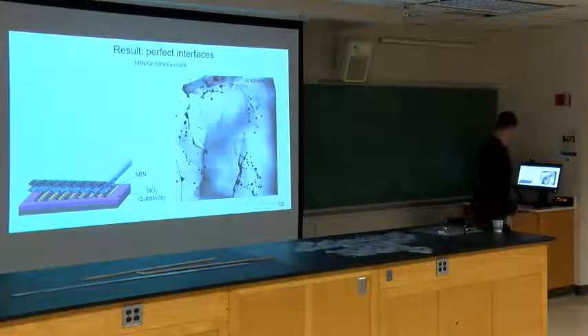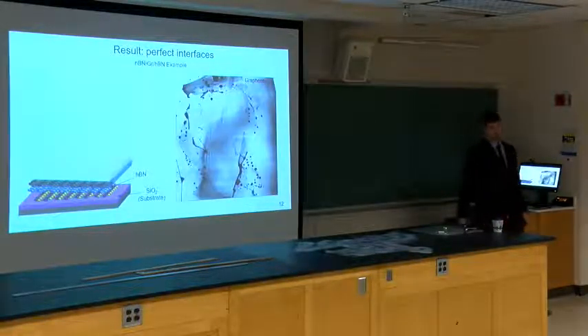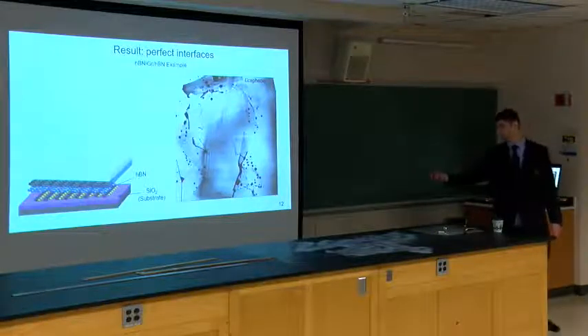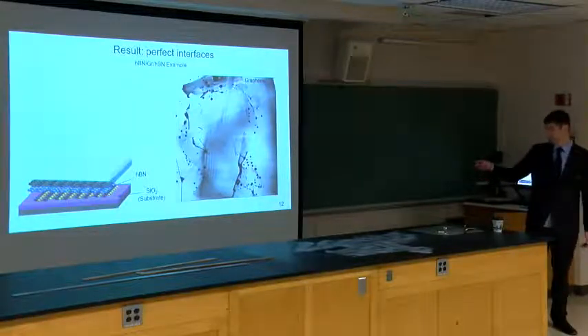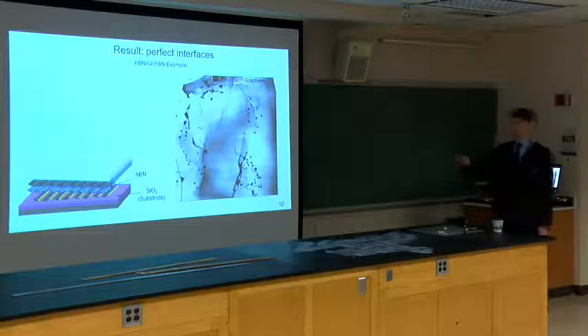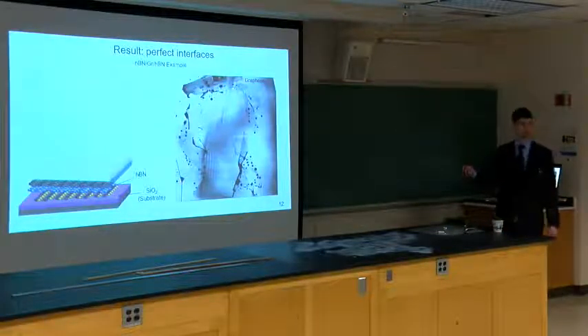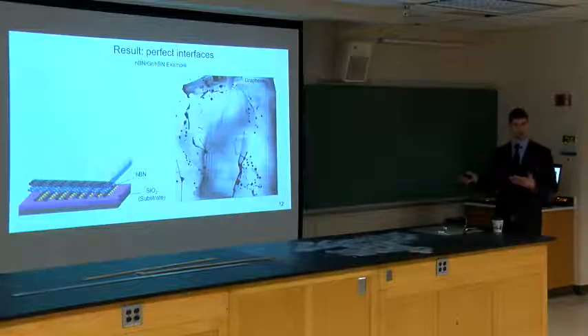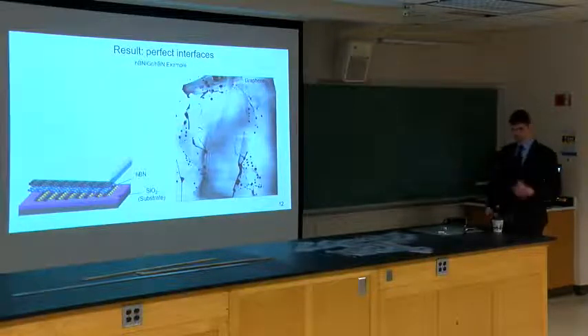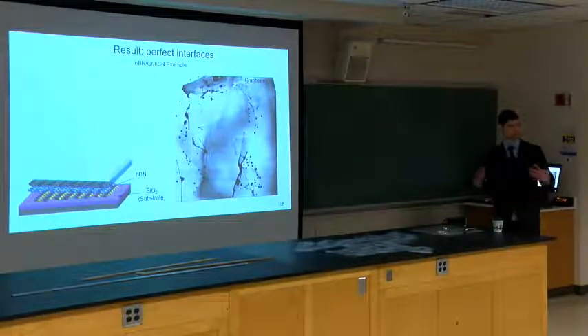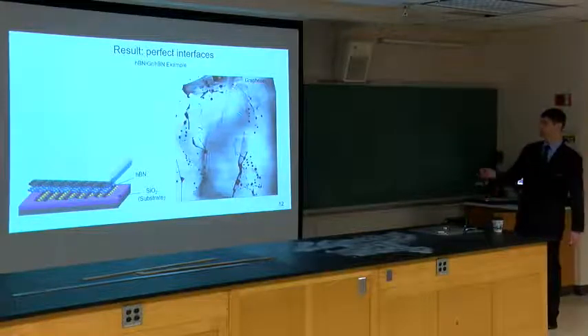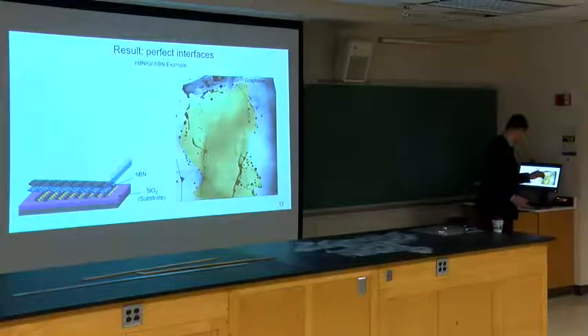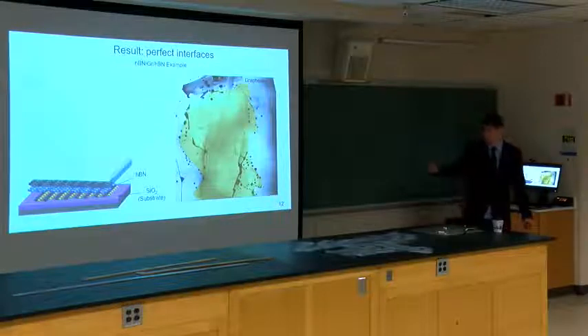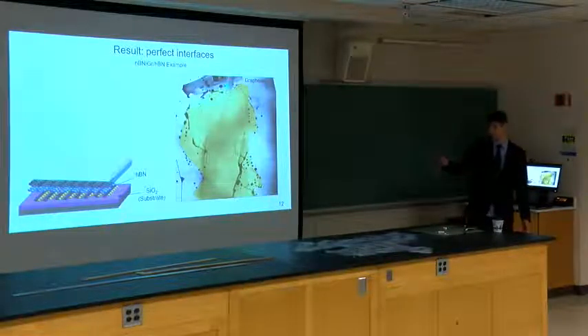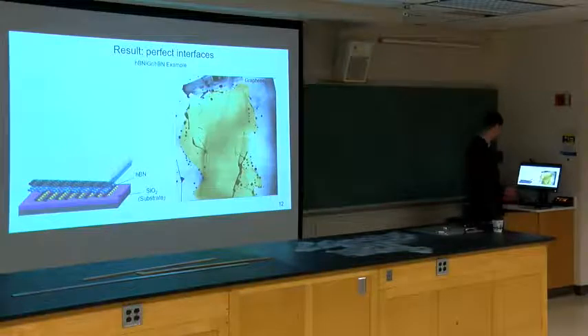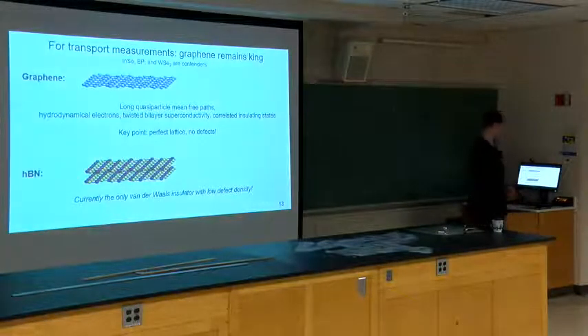So what we end up with is a basically perfect interface. The scale bar on this is not showing, and it's about 2 nanometers from the darkest color to the lightest. So this is really about as perfect as you can get for combining multiple materials together. There's no polymer between it. There's nothing. And the graphene area is defined by this. The part that I'm showing is about 80 microns. So we can make very large stacks that are very, very perfect.